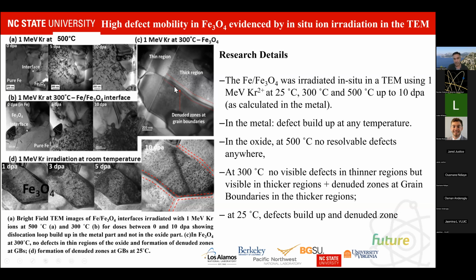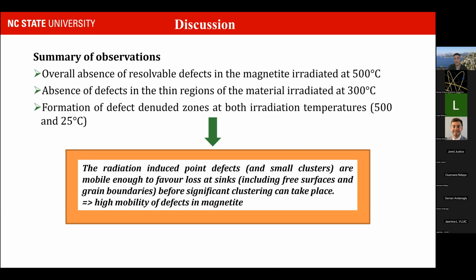What is of interest also is the fact, again, that along the grain boundary you have the denuded zones, and that was also observed at room temperature, and those denuded zones were pretty large, more than 60 nanometers on each side of the grain boundary. Which means that, in the end, the radiation-induced point defects and the small clusters are in fact mobile enough to favor the loss at sinks, including free surfaces or the grain boundaries, before clustering and loop formation take place. That is at least to explain why we don't see defects at 500C and 300C.